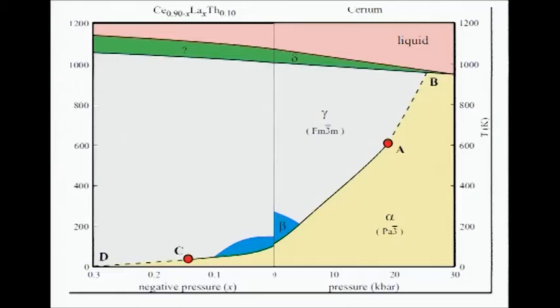The purpose of the thorium is to suppress this pesky beta phase, which is actually metastable. It's kinetically unstable. Pecharsky and Gschneidner showed that it has a half-life of about 800 years. So the thorium is meant to suppress this so that you can look at this transition over here at negative pressure, because the alloying expands the lattice.